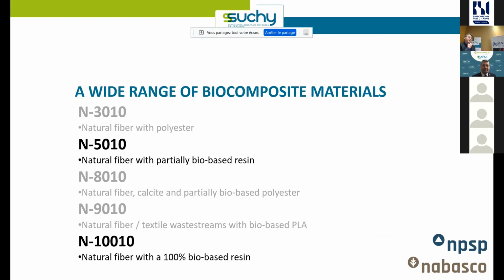If we talk about biocomposites, as I said before, in our lab we can use lots of different techniques to make biocomposite products, from pressing to vacuum infusion to pre-pregging. And within the SUCHY project, we focused on two materials. So the N5010, which is a natural fiber with partially bio-based resin, where we use vacuum infusion or RTM to make the laminate. And the N-10010, where we go to 100% bio-based composites, often in combination with a bio-based resin which uses water as a solvent. So there we use the pre-pregging technology, where we want to have the lowest amount of resin possible.